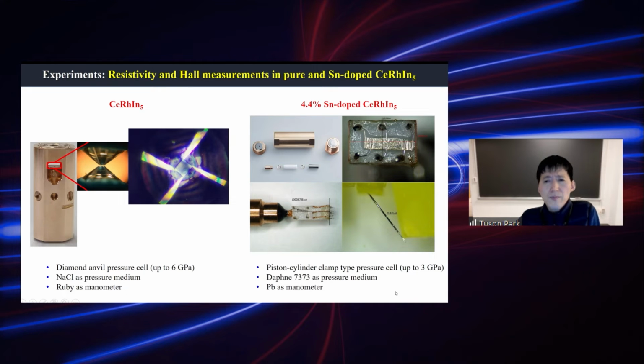The resistivity and Hall measurements: for CeRhIn5, because we need higher pressure, we used the diamond anvil pressure cell and measured up to 6 GPa. For the 4.4% tin-doped compound, we used a piston cylinder type pressure cell up to 3 GPa.